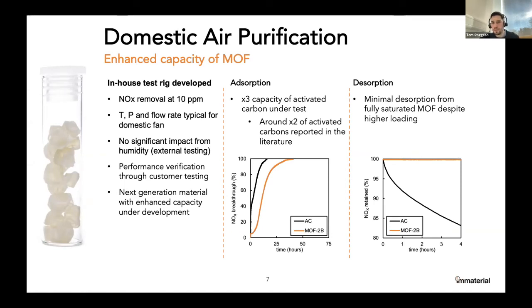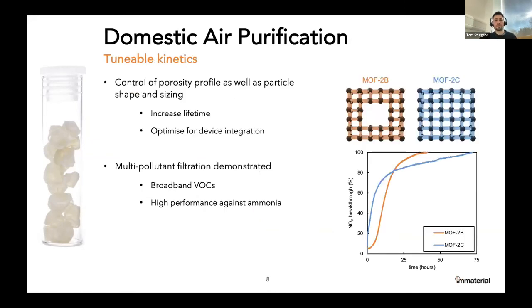One last thing worth mentioning on this slide, and that's relating to some of the comments about the higher risk technologies. One thing we have to be very aware of is potential surface chemistry on these adsorption materials. So NOx is quite a reactive species, and actually with the activated carbon, you initially see a peak of NO rather than NO2 coming through due to some surface chemistry. And again, that's something that we've been able to avoid with our metal organic frameworks, but hence the importance of having a total NOx detector on the end. Our next step is tuning these materials.